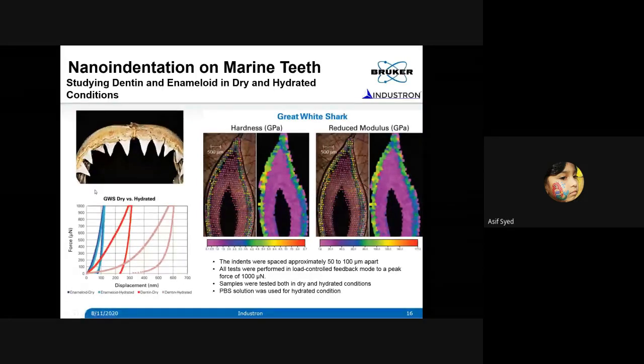On the left side is the load displacement curve. If you look at the load displacement curve, there are two different conditions. One is the hydrated condition, which means you're doing everything inside a submerged solution. Normally we use saline solution, like phosphate buffered saline solution, and we do it in a hydrated condition. For the enamel material, you can see the blue and the light blue curves. You don't see much of a difference in the load displacement curve for this particular specimen in the white shark. But if you look at the dentin material, the red curve is in a dry state, and the pink curve is in a hydrated state, and it loses its property. You can see a big difference from dry to hydrated state in the dentin material, but you don't see much in the enamel material.